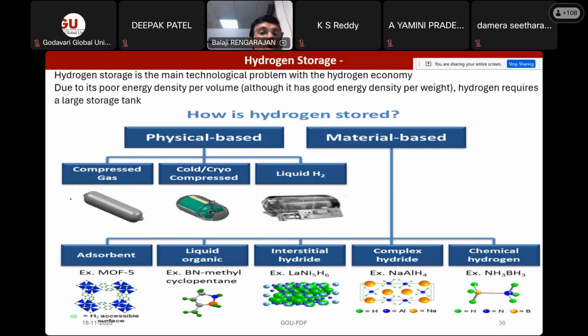But if you want to use these compressed cylinders in transport applications, a commercial cylinder at 150 bar will hold only 0.5 kg of hydrogen. If you want to cover a mileage of 400 or 500 kilometers, especially for transport, you need to carry 5 to 6 kg of hydrogen onboard. But under this 150 bar pressure, you would need to carry 12 to 13 cylinders onboard. So the payload of the vehicle will increase, and that will not give you the mileage, whether it is an IC engine based hydrogen engine or any hydrogen fuel cell based engine. So for hydrogen storage, you cannot carry steel-based cylinders.